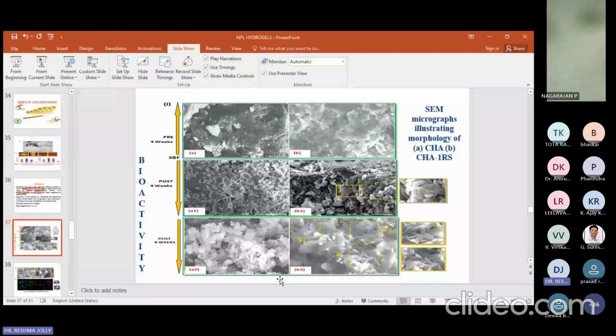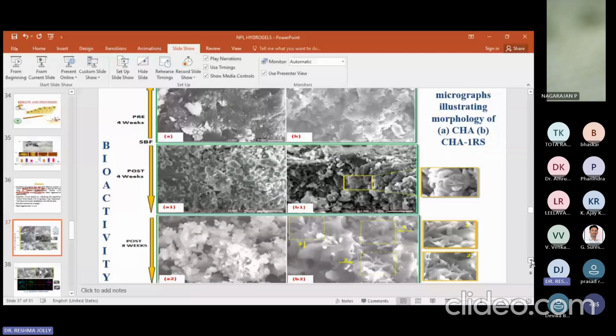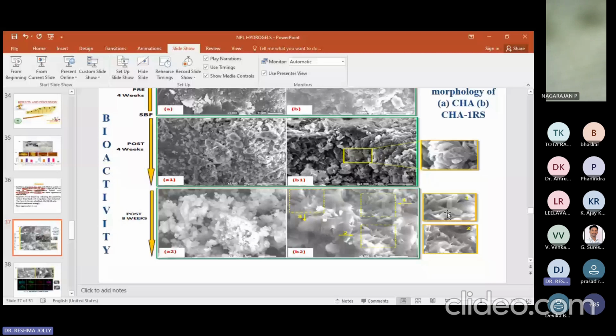And after 8 weeks, this is also showing good apatite formation and deposition. But here, I can enhance it a little bit. You can see how much intermingled apatite formation has occurred. These are wonderful results. You can see clearly that the interfacial interlinking is visible. In this case, only apatite deposition occurred, but here, apatite deposition is occurring with a very special appearance. So this was a very encouraging result after incubating our material for 8 weeks.